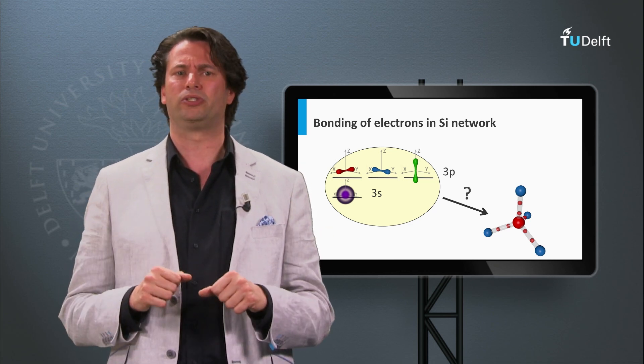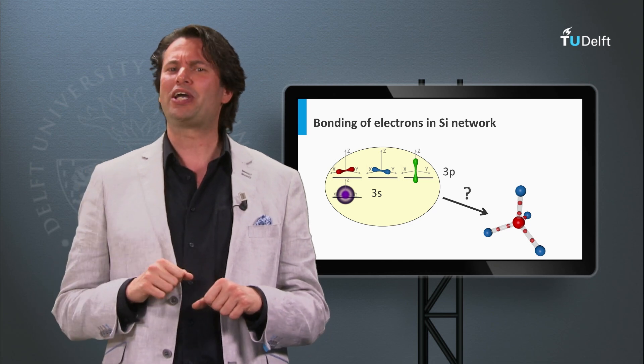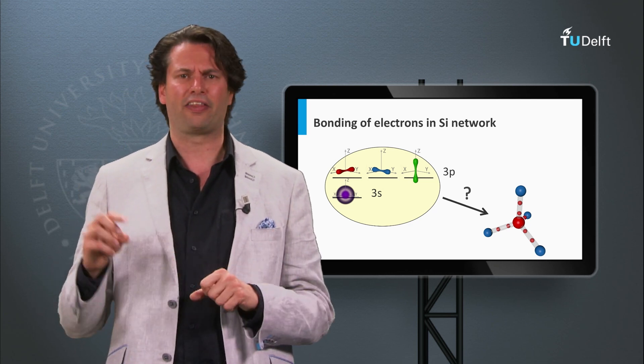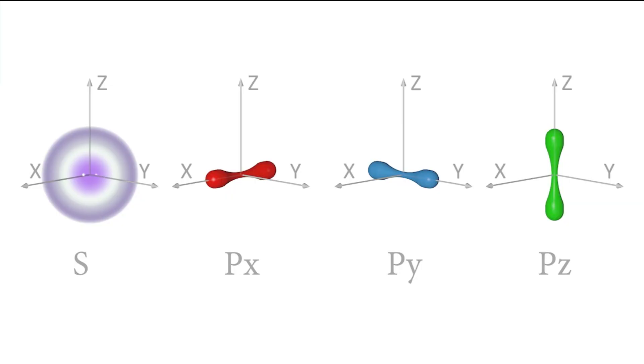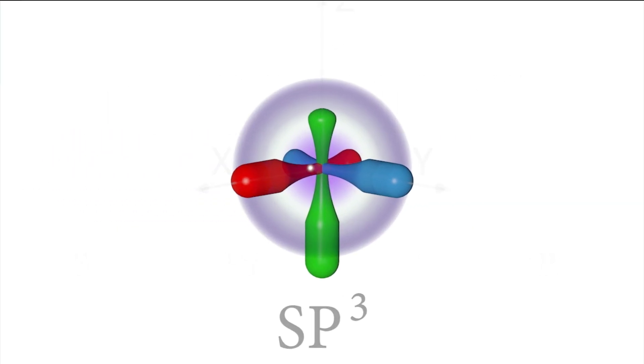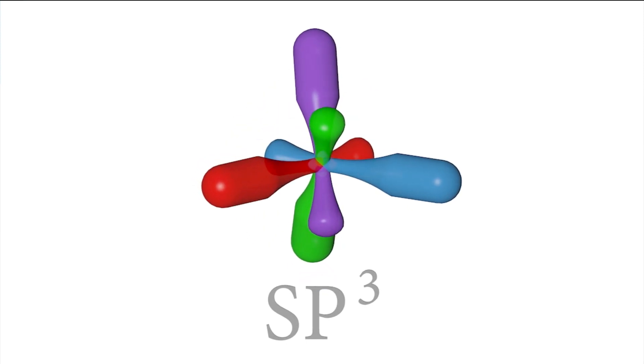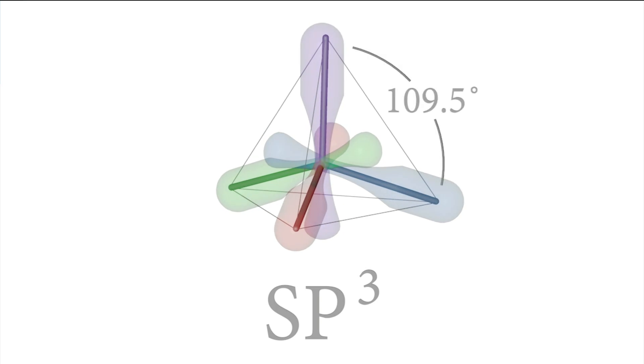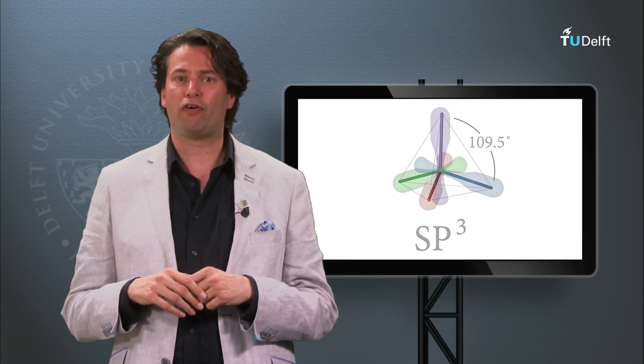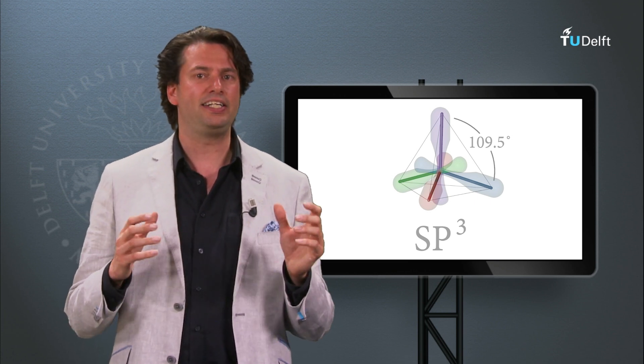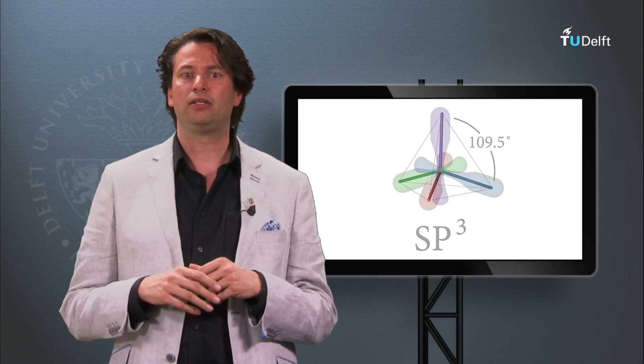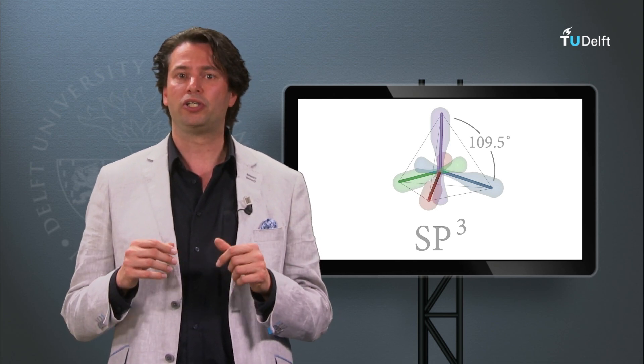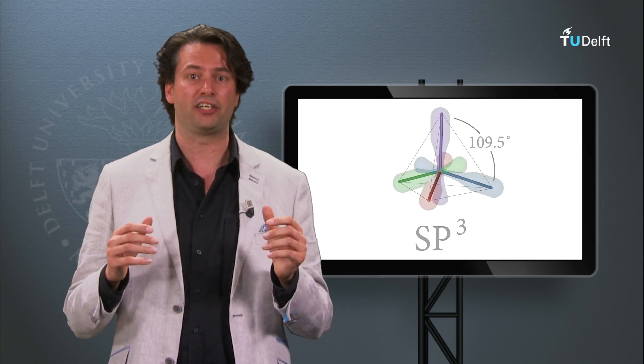To explain this, we consider one electron in the 3s state and three electrons in the 3p state. We now make a cocktail of orbitals — we mix these four states. In nature, it appears that these four states mix into effectively four symmetric states. The animation demonstrates the mixing. The four resulting symmetric states are called the sp3 hybrid. In nature, the four valence electrons behave like they are in these four sp3 orbitals. The orientation between these four orbitals corresponds to the tetrahedral coordination with an angle of 109 degrees between them.